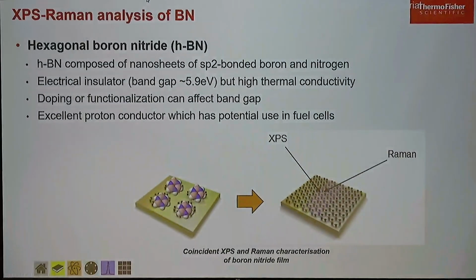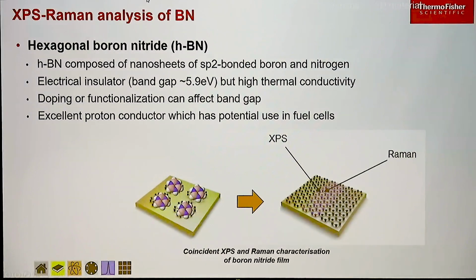Last 2D material, boron nitride. And so again, we're looking at something which is an analog of graphene. But in this case, boron and nitrogen rather than carbon. It's an electrical insulator, but it's got very high thermal conductivity. And the idea that the people who were preparing the sample had was they wanted to use it for an anti-corrosion coating. So they wanted to coat the surface of a copper film with boron nitride to prevent oxidation occurring.